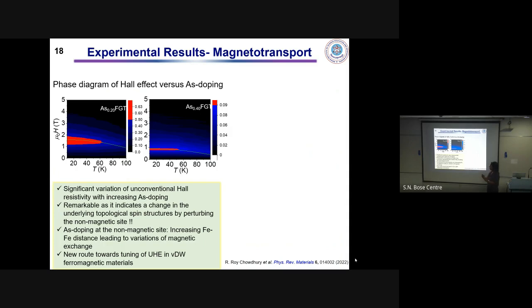One of the possible causes might be that because of arsenic doping, we have observed an increment in the lattice parameter C. From the structural refinement, it has been shown that as a result of arsenic doping, the distance between the Fe1 and the Fe1 within a layer increases, and thereby it leads to the reduction of the exchange interaction, the magnetic interactions, which might bring in such changes even by doping at the non-magnetic site.